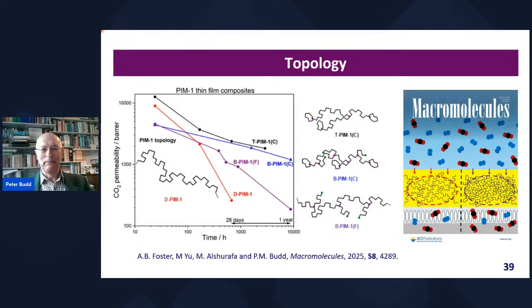Now, recently, Andrew Foster, who's been working at Manchester, has gone through all the literature and all the results we have on thin film composite membranes based on PIM1 to get as much information as possible about the topology of the polymers that were used. Sometimes people didn't realize what they were using at the time, and its effect on the performance. And we see big differences in the performance and the aging behavior depending on the topology of the polymer.